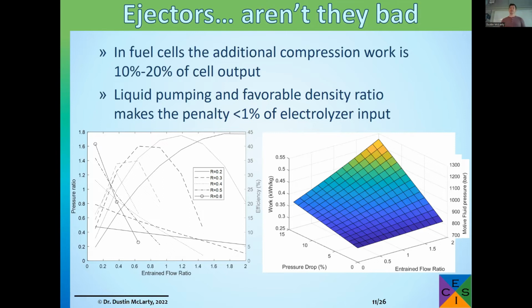And the best you can really do when you use ejectors for recirculation rather than a blower, you're going to pay a penalty for that. And you're going to pay about 10 to 20% of the cell output, because you had to pre-compress all of this hot air going into the system above the operating pressure to really drive that recirculation with the ejector. This is not going to be an issue with electrolyzers, because you're able to do liquid pumping, which is far more efficient at getting to pressure than gaseous compression. It just takes that much less work.